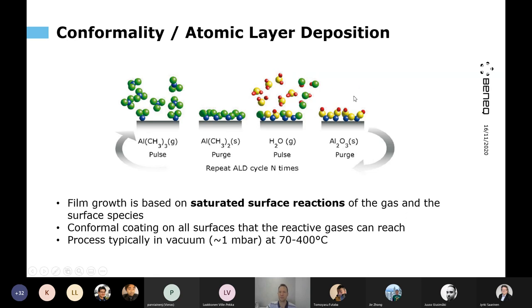Then we will again purge the remaining water molecules away, and we can continue to introduce the TMA again. So what is described here is one ALD cycle, and then we just do as many of those as we want to reach the desired film thickness. Typical growth per cycle, as it said, is about one angstrom, so 0.1 nanometers, when we go through these four steps. So the real benefits and drawbacks of ALD can be derived from this picture.